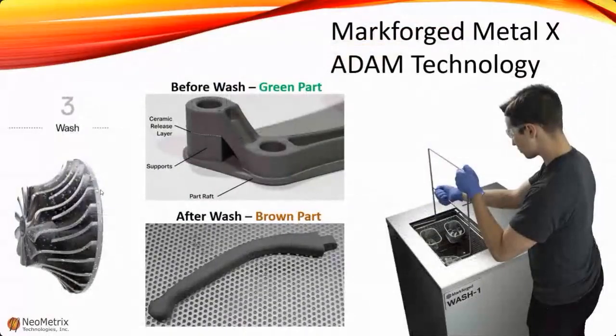In the wash, the first stage of the binding material is removed. The green part is taken from the printer and placed into the wash basket, which is then lowered into the solvent. The solvent dissolves most of the binder material. After washing, it's in the brown part form. It's more fragile than a green part, but still bound together.